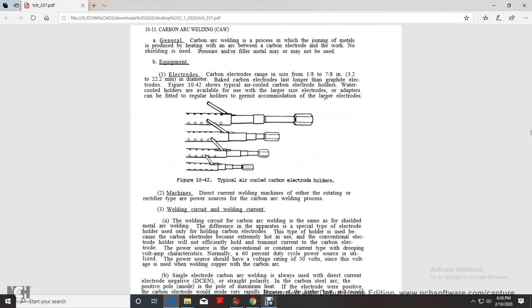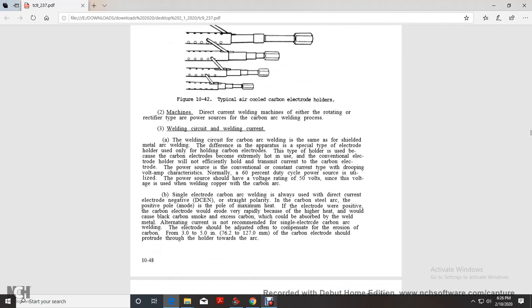Machine: a direct current welding machine, either of the rotating or rectifier type, is the power source for the carbon arc welding process. The welding current circuit for carbon arc welding is the same as with shielded metal arc welding, with the difference of a special type of electrode holder, usually used only for holding the carbon electrode. This type of holder is used because carbon electrodes become extremely hot, and a conventional electrode holder would not efficiently hold or transmit the current to the carbon electrode. The power source is a conventional constant current type with drooping voltage ampere characteristics, normally at 60% duty cycle. The power source should have a voltage rating of 50 volts, since this voltage is used when welding copper with carbon arc.